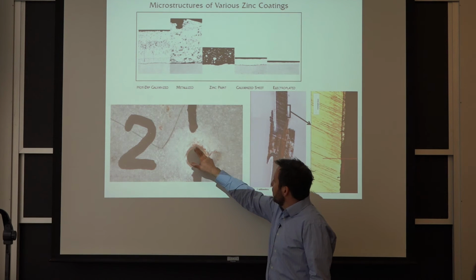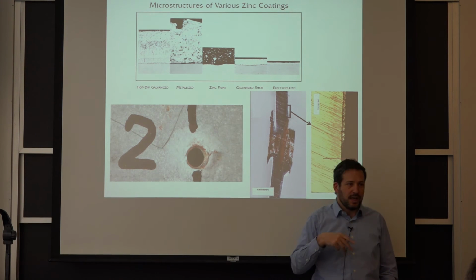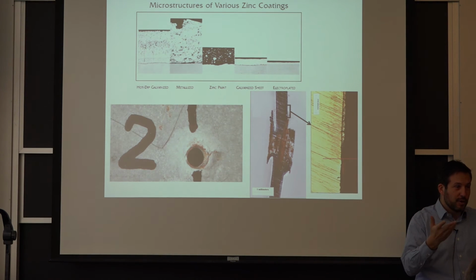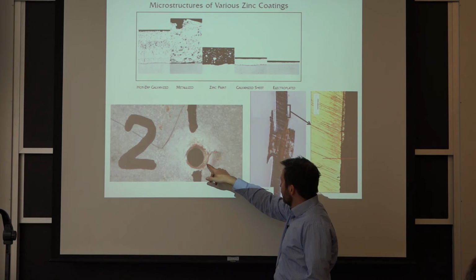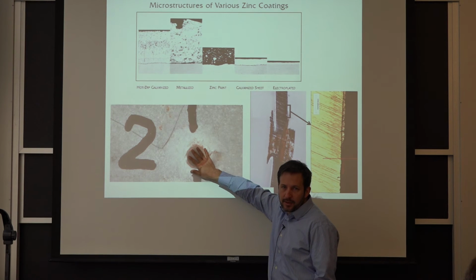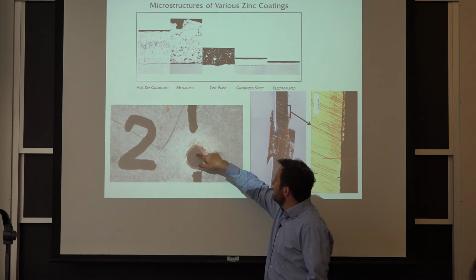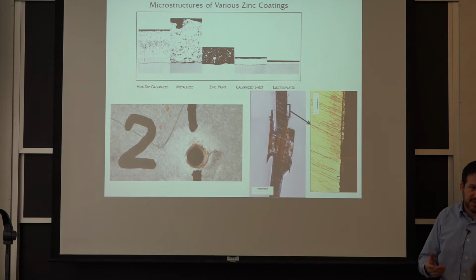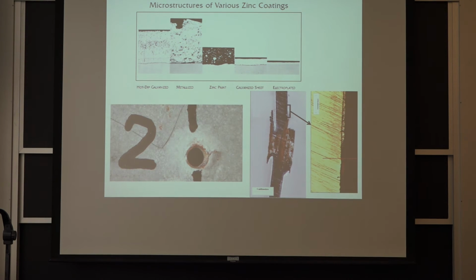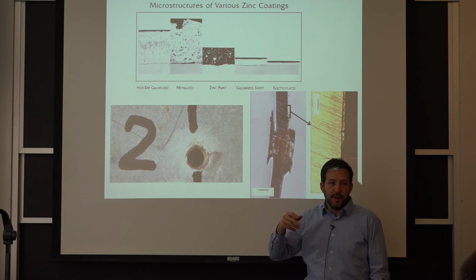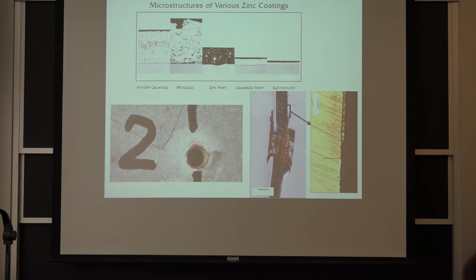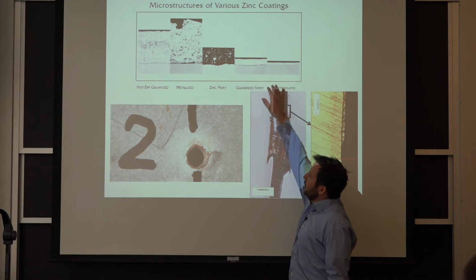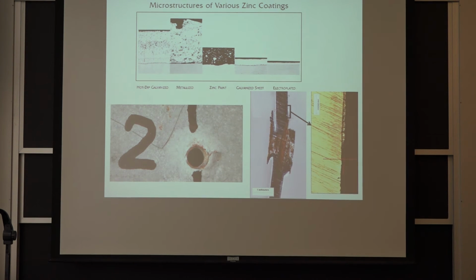What happens here is when it's drilled in place, that's very, very common. So you have self-drilling fasteners, you have your sheet, and you just go wherever you want and install the sheet. So you can use the galvanizing in the vicinity of where the exposed metal is, but that vicinity is of the order of 5 or 6 millimeters for condensation. So in other words, if you're not submerged in water, the cathodic protection effect of the zinc can only go so far. It will only go to the extent of a film or a droplet of water, and that's millimeters. So it's a very good example of an application where, if you expect a lot of moisture and you're thinking about long-term service, you can't use these thinner electro galvanized samples. And of course, they're a lot cheaper.